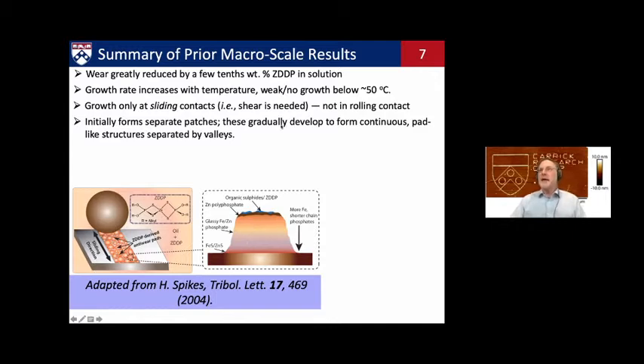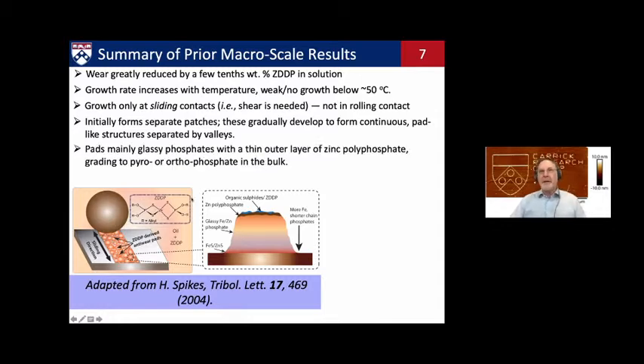They sort of form continuous pad-like structures separated by valleys, whose structure has a graded composition and graded properties. It's a glassy phosphate with sort of a thin outer layer of zinc polyphosphate, and it grades to shorter chain phosphates deeper in the bulk with some sulfur that's clearly helping attach it to the surface. It grows to anywhere between 50 to 150 nanometers thick, depending on conditions, but then levels off.